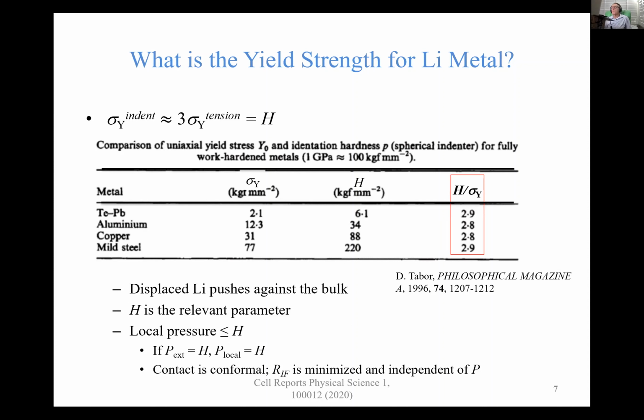So then the lithium will flow so that the pressure is equal to the hardness everywhere. At that point, contact is conformal. And also at that point, the interfacial resistance is minimized because it's in contact everywhere. And it's also independent of pressure, because pressing harder doesn't get you better contact once you're conformal.